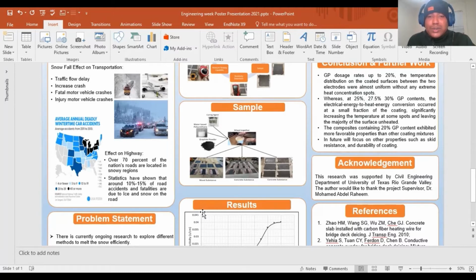Wood substrate was used because the electric conductivity of dry wood is low enough to ensure there was no interference with conductivity measurement. Air-dried Portland cement concrete substrate was used to simulate the real condition in the intended application of this coating material on PCC pavement.